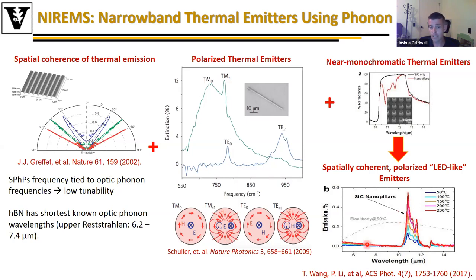And now by doing this, if you combine all 3 of these, and you could do this in a single package, you could potentially realize a spatially coherent, polarized, narrow band source in the long wave infrared, which would operate like an LED, but not require any active region. It would be basically just a simple nanostructure design with a local heat source.